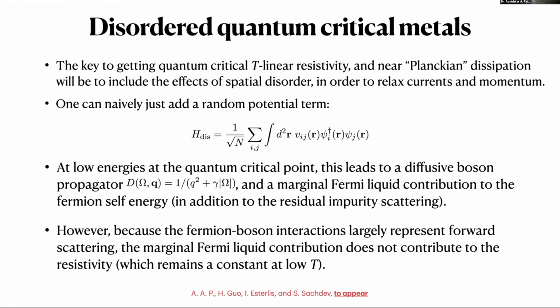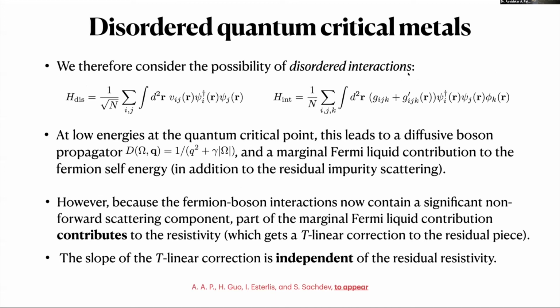That comes in addition to residual impurity scattering of the fermions. However, because the fermion boson interactions are dominated by Q equals 0 bosons, it's largely forward scattering and no current is relaxed. So there's no T-linear correction to the resistivity, which remains a constant at low temperatures. So to get T-linear behavior, we consider the possibility of having disordered interactions. So where in addition to the potential disorder, we can consider the disorder occurring in the interaction coupling between fermions and bosons. So you have a uniform G and a G prime that is disordered and random in space.